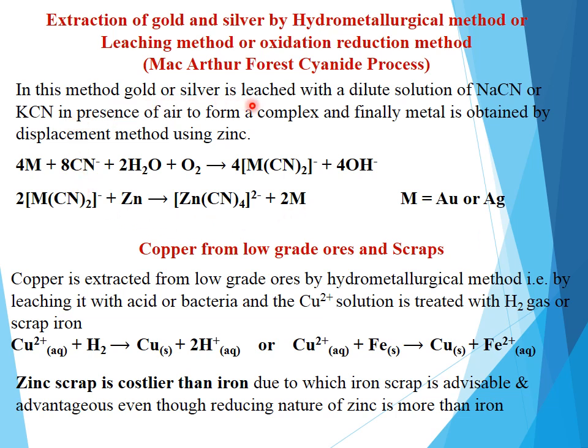In the first step, gold or silver is leached or treated with a dilute solution of sodium cyanide or potassium cyanide, and air is passed, due to which gold or silver turns into a sodium or potassium cyanide complex. Later on, that complex solution is taken out and treated with powdered zinc. Zinc displaces gold or silver and you get a precipitate of gold or silver.